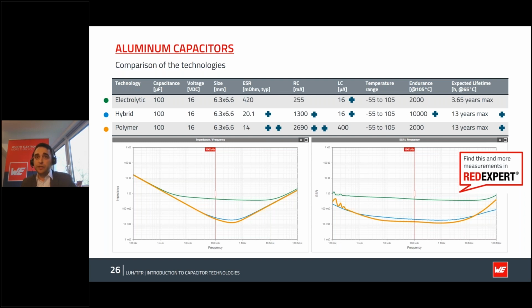On the other hand, you see the electrolytic has very low leakage current, so very good, and the hybrid basically can take 100% of that advantage with them, but the polymer is rather poor with 400 microampere here. When it comes to lifetime, you will see that the hybrid part with 10,000 hours is by far the best, looking at the data sheet.